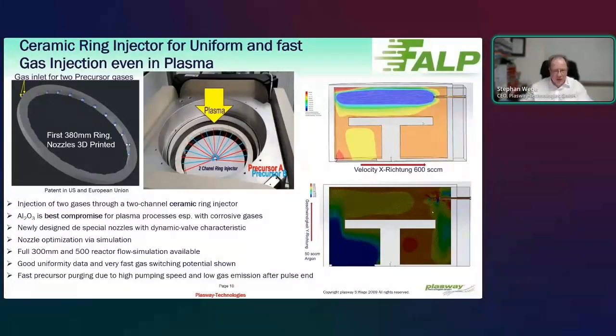This was extremely important to be very fast, because then we don't need to clean, we don't need to pump out the interaction channels. But what you can see already here, we were able to bring in the gases very nicely. But in this case, this old chamber has a turbo pump that is not sitting symmetrically. It is sitting by the side. So you can already see, at least when we turn off the gases, that we don't have a perfect gas distribution function.